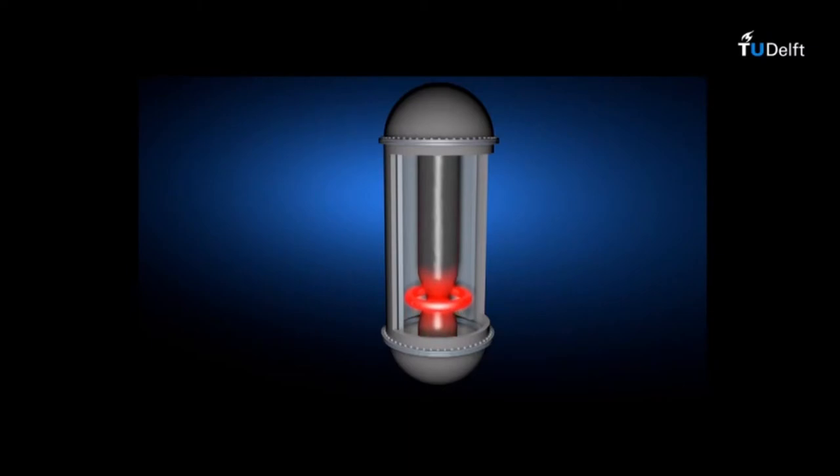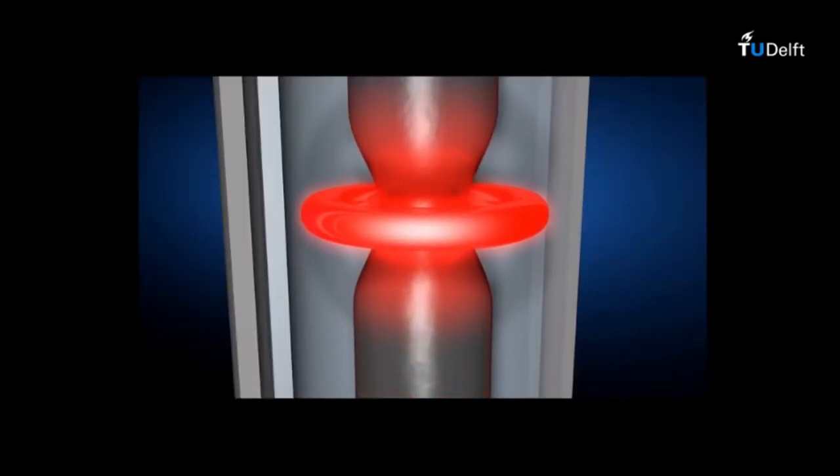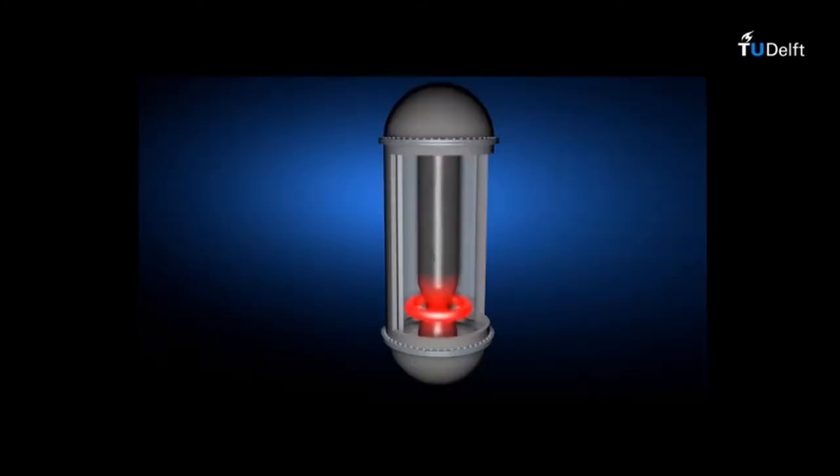The melted part is put in contact with seed crystals. Here it solidifies again and adopts the orientation of the seed crystal. Again, both 100 and 111 orientations are being used. As the molten zone is moved along the polysilicon rod, the single crystal ingot is growing as well. Many impurities remain in and move along with the molten zone. During the process nowadays, nitrogen is intentionally added, which improves the control on micro defects and improves the mechanical strength of the wafers.